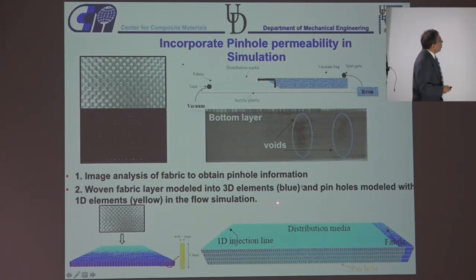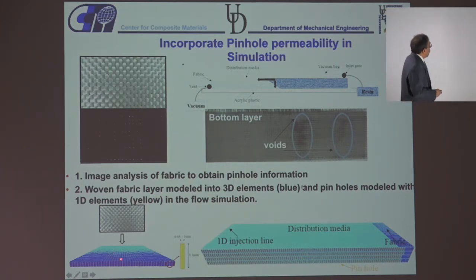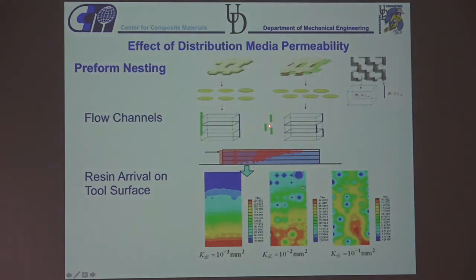And so what we did is we said, let's see if we can model this. So we actually started introducing a stochastic way of modeling it. So what we do is basically we can put in pinholes. So this is our distribution media on top. These are our fabric layers, and I can put pinholes at different locations. So by taking a picture of my fabric, I can use a Gaussian distribution or some sort of a distribution to lay down the pinholes, and then I can look at how the flow from the distribution media is going through the pinholes. So here the pinholes are laid randomly, and you notice that if you have a distribution media that is very, very permeable, which means this is the most permeable distribution media, you get the spotting effect.